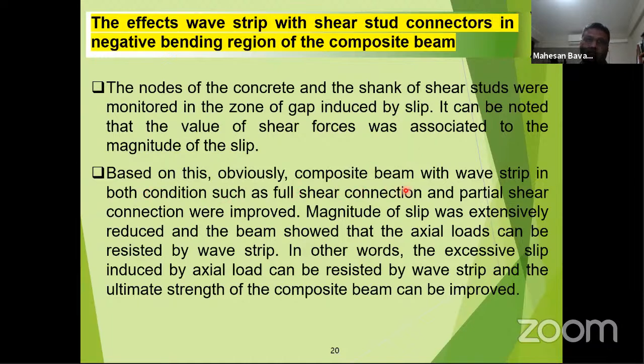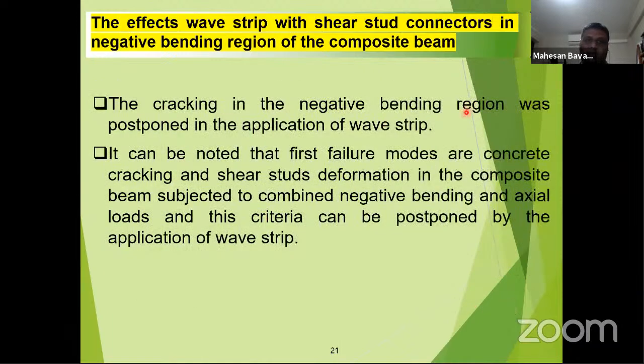Based on this, obviously the composite beam with wave strip in both conditions, full shear connection and partial shear connection, was improved. The magnitude of slip was extensively reduced, and the beam showed that the axial load can be resisted by wave strip. In other words, the excessive slip induced by axial load can be resisted by wave strip, and the ultimate strength of the composite beam can be improved. The cracking in the negative bending region was postponed by the application of wave strips. It can be noted that the first failure modes are concrete cracking and shear stud deformation in the composite beam subject to combined negative bending and axial loads, and this criterion can be postponed by the application of wave strip. This we found based on the research.